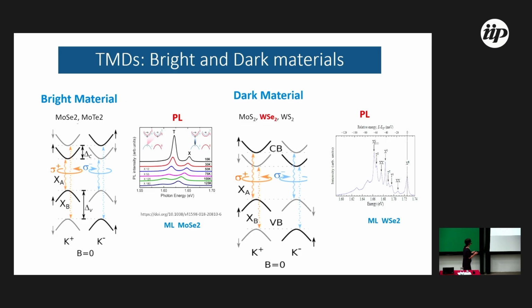And furthermore, in these transition metal dichalcogenide materials, we have two groups. One group we call bright materials, because for the selection rule, you need conservation of spin and conservation of momentum, and the fundamental transition is spin allowed. And when you measure PL, we have an exciton and a trion at different energies. And there is another group where the fundamental transition is spin forbidden, because you change the spin of the bands. And these materials are called dark materials.